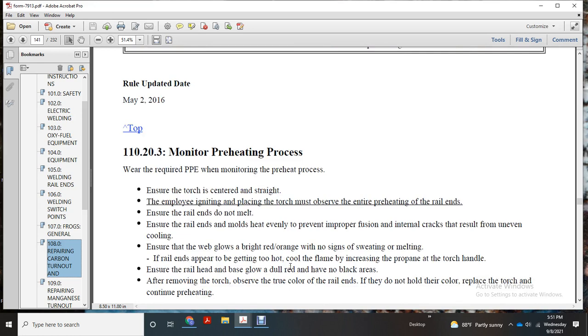Monitoring the preheating process. Wear the required protective equipment when monitoring the preheat process. Ensure the torch is centered and straight with the rail. The employee igniting the torch must observe the entire preheating of the rail ends. Ensure the rail ends do not melt. Ensure the rail ends and molds heat evenly to prevent improper fusion and internal cracks as a result of uneven cooling.